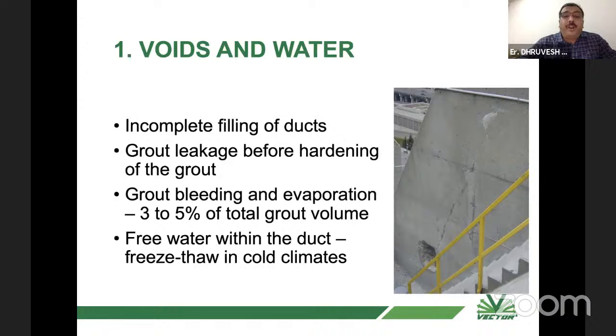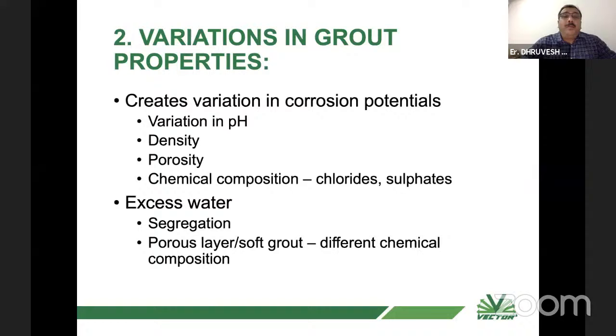And when free water within the duct freeze-thaws in cold climate or in other conditions, it creates further issues with the tendons. There can be a variation in grout property. While pumping the grout, if you have excess water, there can be segregation, and the bottom dense portion will have more hardened grout than the top portion. There can be a variation in pH, density, porosity, chemical composition. Various reasons are there because of which you have different characteristics of grout.